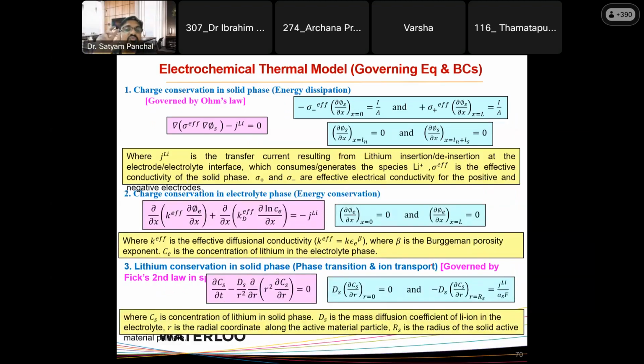The different governing equations used for electrochemical modeling are, first, the charge conservation in solid phase, basically governed by the energy dissipation, which is given by this equation, and boundary conditions at x equal to 0 and x equal to Ln plus Ls, meaning negative plus separator, are provided over here. Here J is the transfer current resulting from lithium insertion and de-insertion at the electrode electrolyte interface, which consumes or generates the species, and the effective conductivity is given by sigma effective. Then charge conservation in the electrolyte phase is given by this equation,